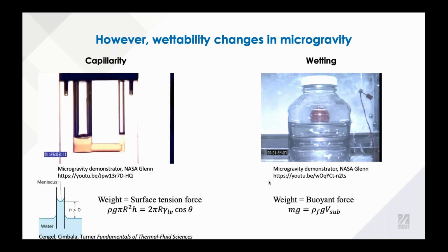Here, typically when we have a hydrostatic sort of problem, we have weight that is balancing out the buoyant force, and that's determining how far into the water, in this case a ping pong ball, will fit. But we see that there's gravity on both sides, so when we have very low gravity, then these forces become really small, and the thing that ends up dominating is our surface tension force, our wettability, which normally under Earth's gravity we neglect in this case. And so there are things that start becoming important in microgravity that we don't consider on Earth.